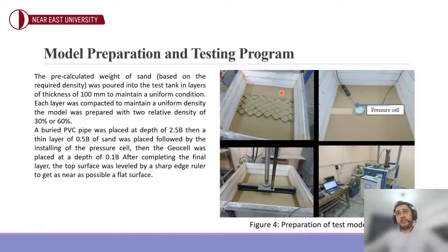Model preparation and testing program. A pre-calculated weight of the sand was poured inside the tank in different layers. Each layer thickness was 100 mm and each layer was compacted to achieve the required relative density. In this research, we have performed two sets of tests. The first set was performed using a 30% relative density as a loose sand, and in the second set the relative density was taken to be 60% as a medium sand.